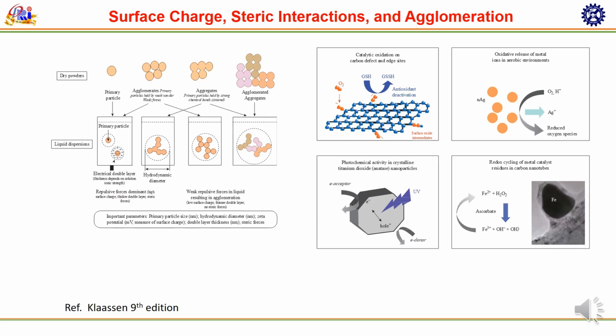Their surface reactivity mechanisms: catalytic oxidation on carbon defect and edge sites. Nanoparticles with a carbon surface can catalyze the deactivation of antioxidants like glutathione, and this causes oxidative stress in cells. Oxidative release of metal ions: in aerobic conditions, nanoparticles release metal ions. These ions interact with oxygen and proteins, producing reactive oxygen species. Reactive oxygen species cause oxidative stress, damaging DNA, proteins, and membranes.